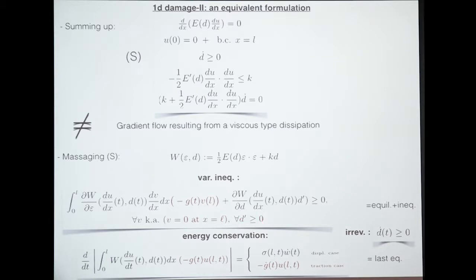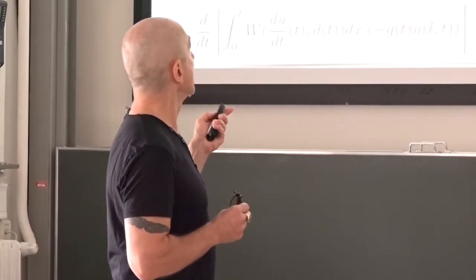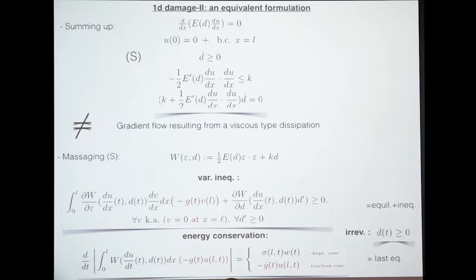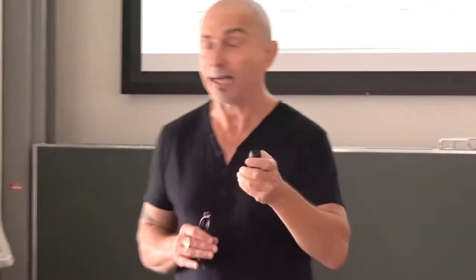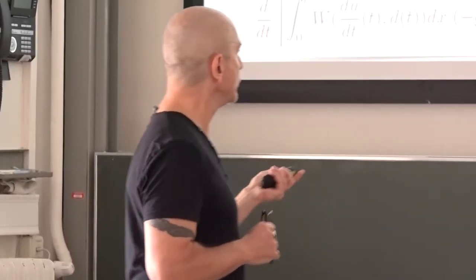D prime should be non-negative, and this is kind of what's left of the constraint that D should increase with time. So this is this variational inequality that you get, and on top of it, you get energy conservation. Not formally, it's energy conservation. There's no missing energy, nothing. And I insist on this because it seems to be lost in what people have been doing.